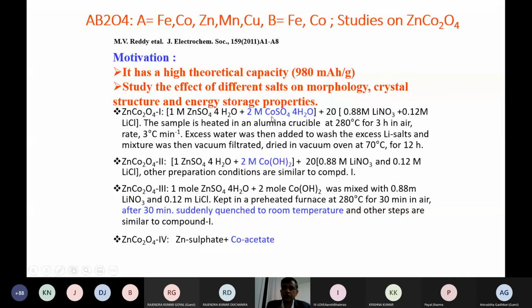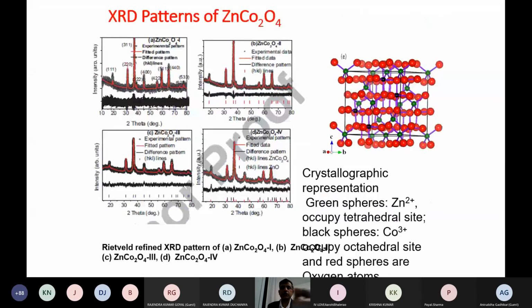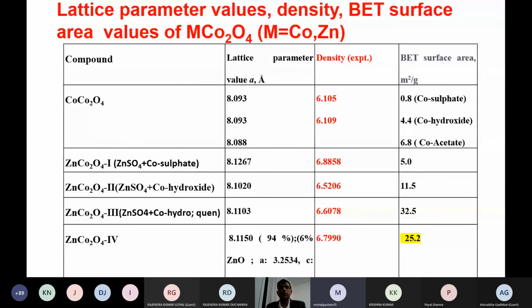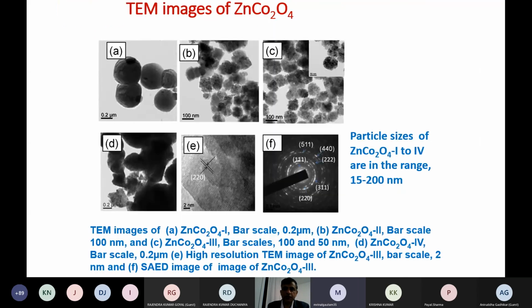What I'm going to suggest here is that by varying the salt, for example cobalt sulfate or cobalt hydroxide, or depending on the quenching speed, we can see differences. In some cases we can see a composite oxide, in the sense that we can see two types of phases. In another case with quenching, sometimes we can see a small impurity of zinc oxide. So in summary, this is useful to see the difference in the lattice parameters, the density of the samples, and at the end the BET surface area.